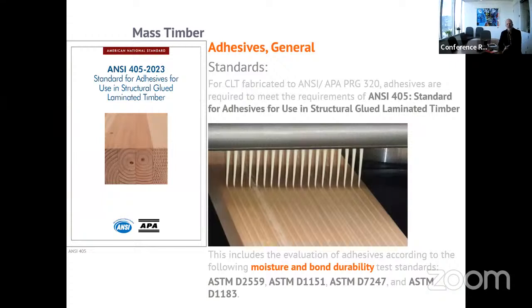There was a good question earlier about adhesives, and adhesives are important not only for the structural capacity of the wood, but they need to maintain their strength both during the high moisture periods of life of the wood. When the panels are originally adhered together, the adhesive needs to continue to perform as the moisture leaves that wood during its drying. Then the adhesive needs to maintain its strength even under situations where that panel or structural member may be exposed to moisture in the field. Additionally, the adhesive has to remain strong in the event of high temperature during a fire event. And also, we have some of our architects wanting that the adhesives are clear and not easily visible. And I'll talk about that a little bit later.